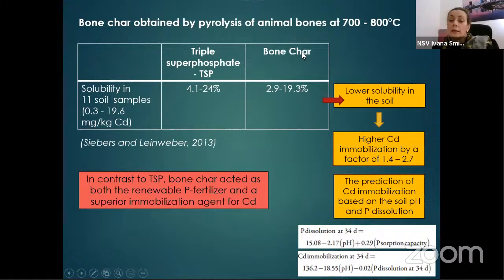There was also a study in which the bone char effect on metal stabilization, in this case cadmium stabilization in 11 different soil types, was compared to the effect of the triple superphosphate, or TSP, the conventional phosphate fertilizer. It was concluded, first of all, that the bone char solubility is always lower than the solubility of the TSP. But on the other hand, the effect on cadmium immobilization was higher by a factor of 1.4 to a factor of 2.7 using the bone char. And this study had revealed that the bone char can be used for the rehabilitation of the soil as an innovative phosphate fertilizer and also as a superior immobilization agent for cadmium.